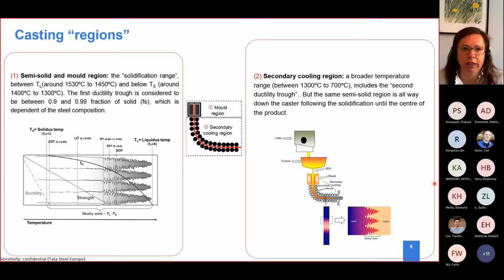If we focus a little bit on continuous casting, basically we have two regions. The first region is the mold region, where the steel starts to solidify and the slab is born. The temperatures we handle at this stage are rather high, normally between liquidus temperature and solidus temperature. Both of them could vary a lot depending on the steel composition. And on the mechanical side, here is where we have the first ductility trough, and it is considered to be between 0.9 and 0.99 fraction of solid. Again, it's very dependent on steel composition.